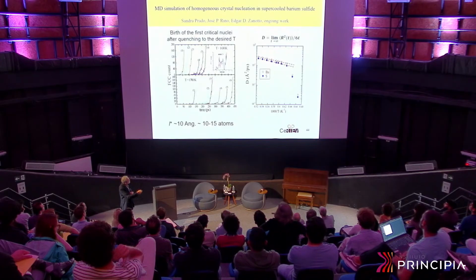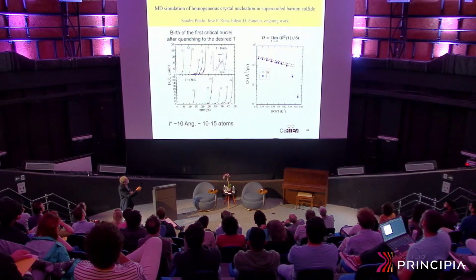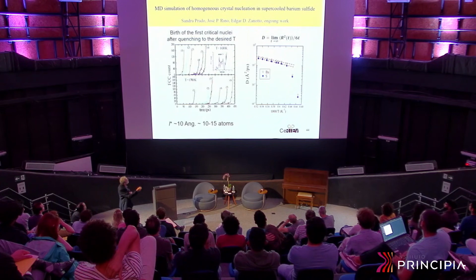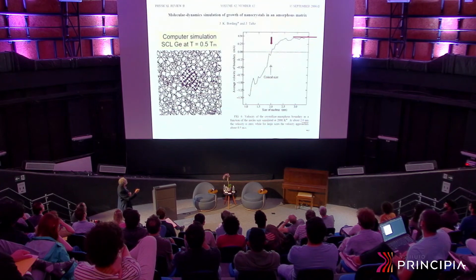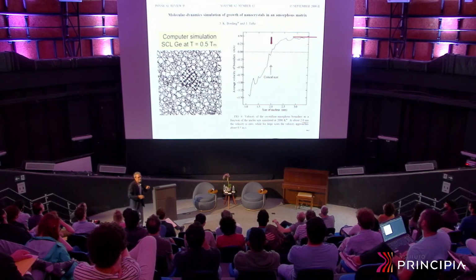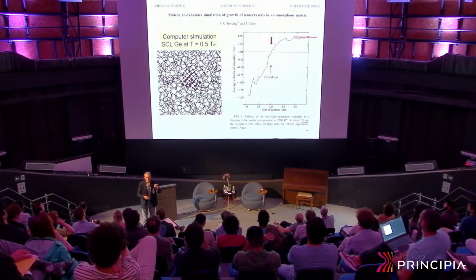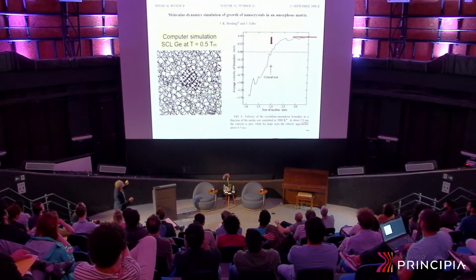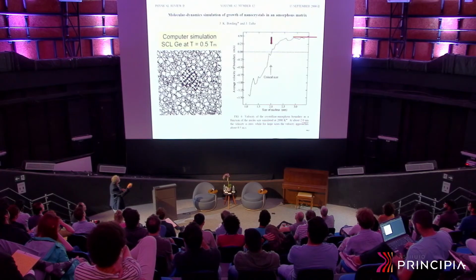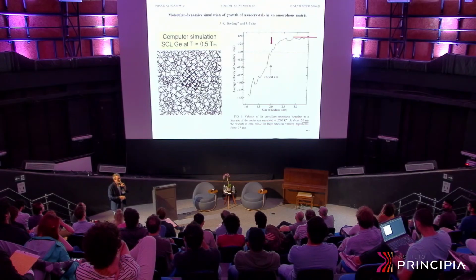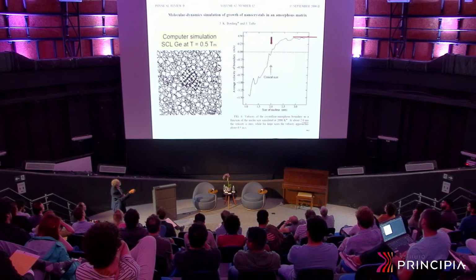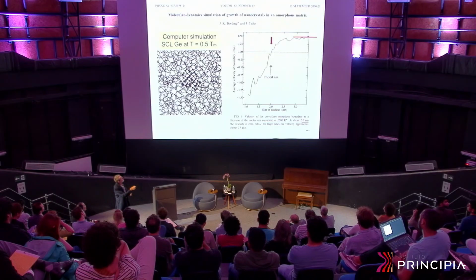Then the material crystallizes, the diffusion coefficient drops. But this is the supercool liquid area. We get the nucleation rates, diffusion coefficients, and then there is one missing thing, the interfacial energy. How can we get the interfacial energy? These guys in Sweden had a very nice idea. You can insert an artificial critical nucleus in a supercool liquid and test the growth velocity, not the nucleation. You have nucleated artificially. Test the growth velocity. If the growth velocity is negative, it's because this cluster is dissolving. If it's positive, it's growing.